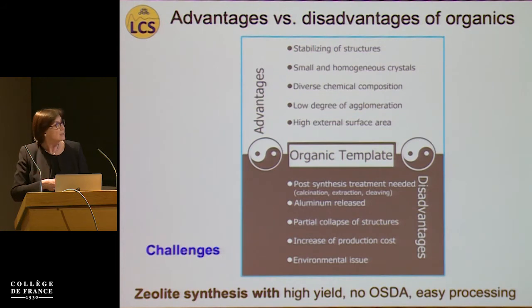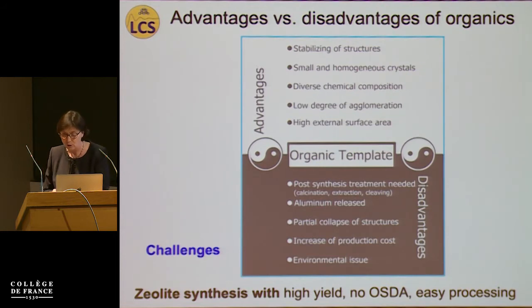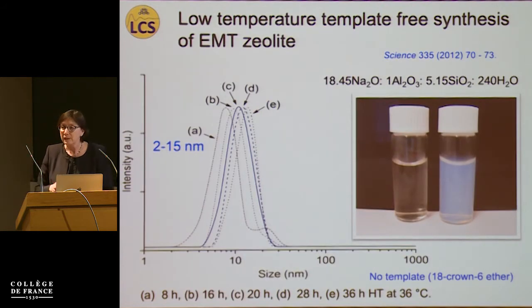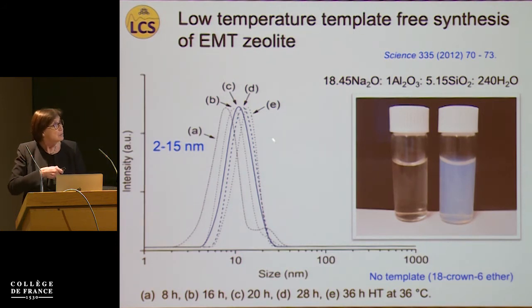As disadvantages, I have to mention that post-synthesis treatment is always required, such as calcination, extraction, or cleaving. And this post-synthesis treatment leads in most cases to aluminum release or partial collapse of the structure. And of course, using organic structural directing agents, we always have to connect with environmental issues and increased production cost. Therefore, during the last several years, we have tried to completely replace the organic structural directing agents with inorganic cations.